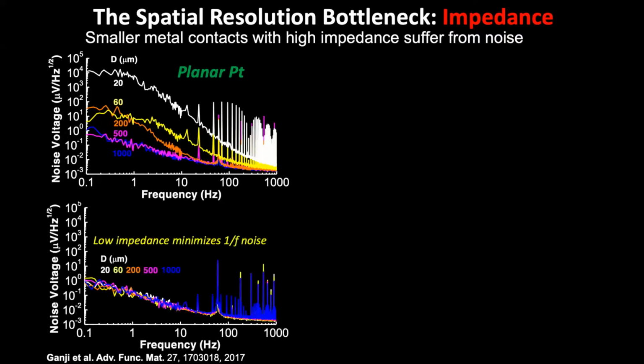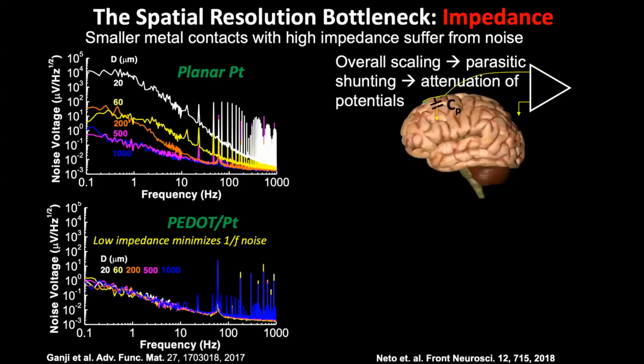This is with planar platinum, but if we use low impedance materials, such as PEDOT, for example, or platinum nanorods, which I will talk about later today, we can overcome this problem because of the large surface area, a lot of absorption sites that minimize the 1/f noise, so that the overall noise, when you scale the contact diameter from 1 millimeter to 20 micrometer, is dominated by the amplifier noise, right? So it's not the contact noise anymore.